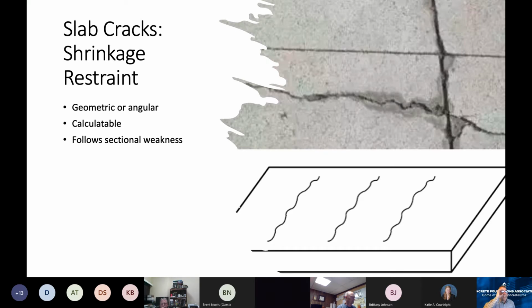Now, where we'll also see this, you can see this pretty easily also in a basement slab. Basement slabs are notorious for cracking because the slab itself is placed well after the walls, and oftentimes after the house is under construction. The first floor framing's on, and they're closing up the house, and then they come back and pour the basement slab. And so as it begins to shrink, it's confined by friction along the side walls where it's trying to move laterally, and if you don't have an expansion material, that friction along the wall is sufficient to cause the crack to develop based on where its friction exceeds the modulus of rupture of the cross section.